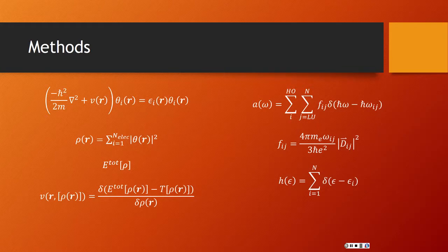Is it reasonable? What do you know about silicon? It doesn't seem completely unreasonable to me, because silicon is known to not really emit light. We say it's not a direct band gap semiconductor, so actually low transitions would not be optically active. Okay. All right. More questions to Nathan?